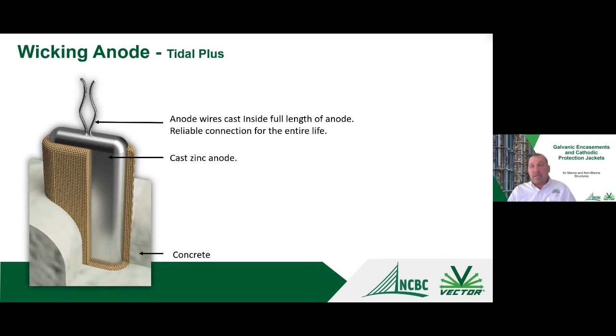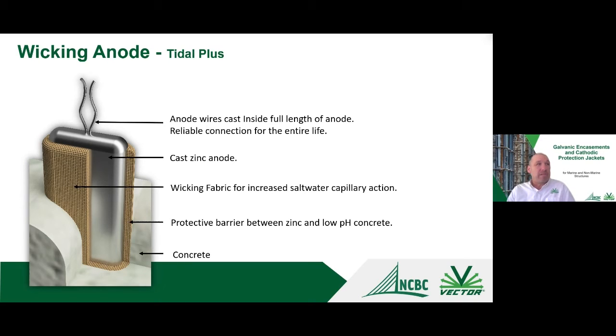And basically, it's a very, very similar system. So it's a cast zinc anode, very similar to the expanded zinc anode, except this is just a larger bar of zinc. And then there's a wicking fabric that's placed around it. This wicking fabric is there so that the salt water can flow up and down this fabric using capillary action. And this allows the zinc to always remain in a wet state, or it's always wetted with salt water. So this is going to keep it in an active state.